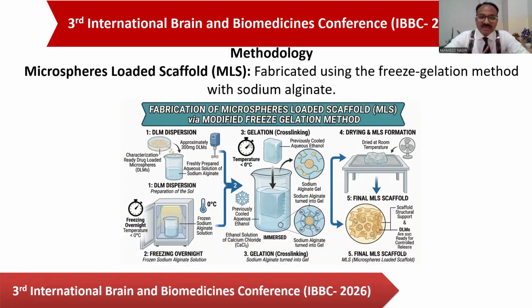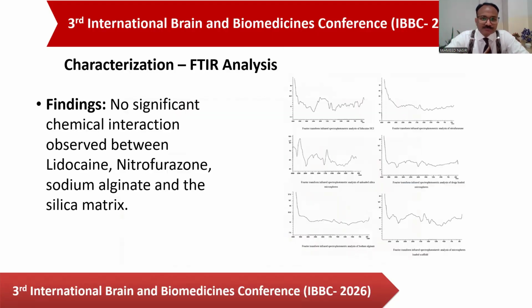After a specified time, the frozen sodium alginate which was immersed into the solution was taken out and dried at room temperature, and I obtained the drug-loaded microspheres. Then they were loaded into the scaffold. So finally, I got the scaffold which contains the microspheres in which dual drugs were successfully loaded.